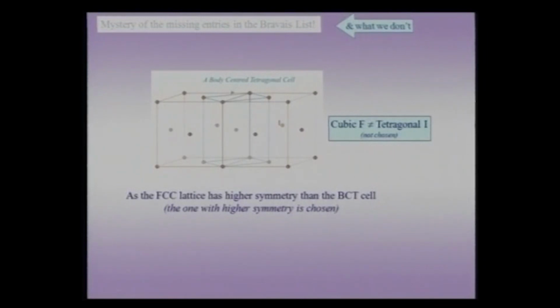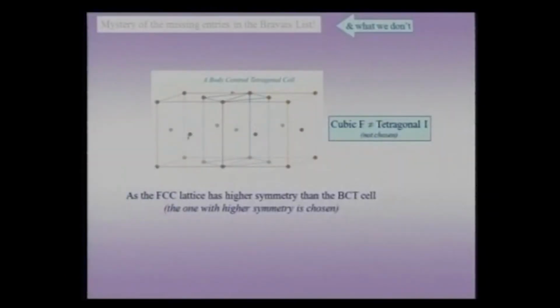The lattice will always remain a face centered cubic lattice, because it has the symmetry of a cubic lattice, and it can be described by a unit cell which has that kind of centering along all the faces. However, for some reason, if you want to make a choice which is given by the blue outline and call it a body centered tetragonal unit cell, yes, you are fine to do so,